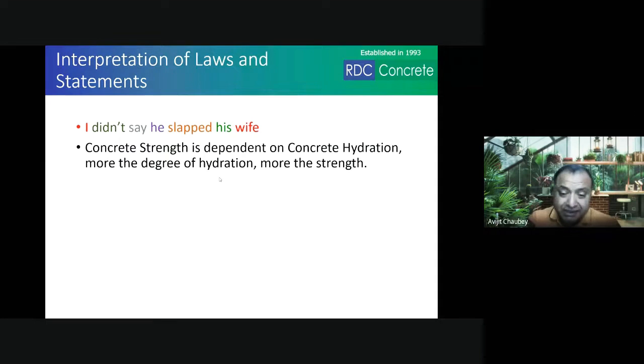But to get higher strength, each cement particle should not hydrate fully. Only the surface should hydrate, and it may form a CSH gel and lock with the other cement particles, but the internal particles should be intact, and that is how you will get a high strength if you are looking for high strength.